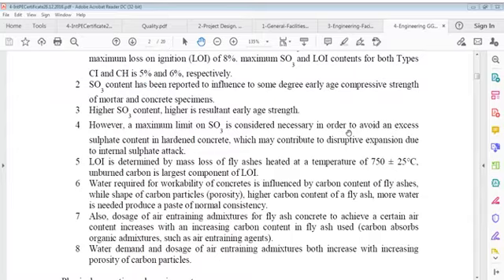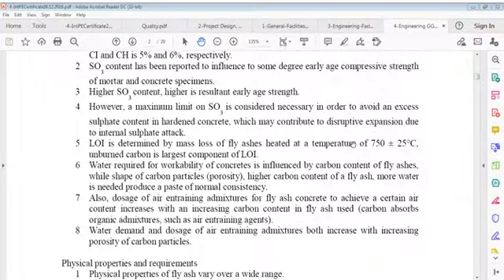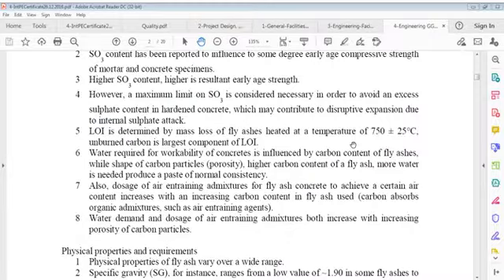SO3 content has been reported to influence, to some degree, the early age compressive strength of mortar and concrete specimens. Higher SO3 content results in higher early age strength. However, a maximum limit on SO3 is considered necessary to avoid excess sulfate content in hardened concrete, which may contribute to disruptive expansion due to internal sulfate attacks. So concrete must have a boundary for how much sulfate content is acceptable.